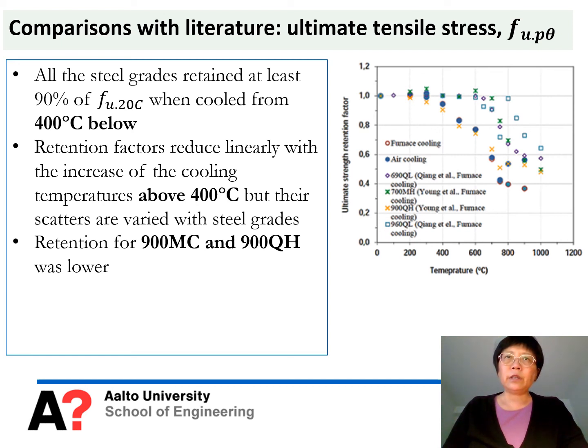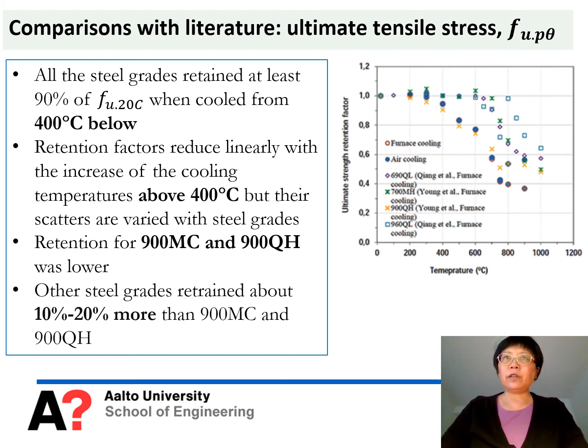So for the S900 steel grade, the retention was the lowest. And for other steels, the difference can be 10 to 20% at different temperatures.